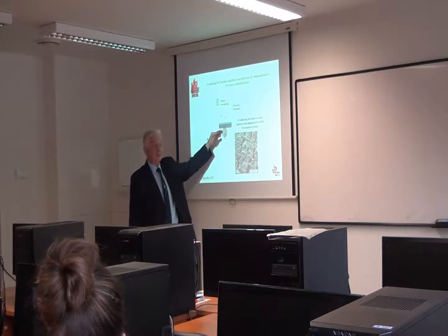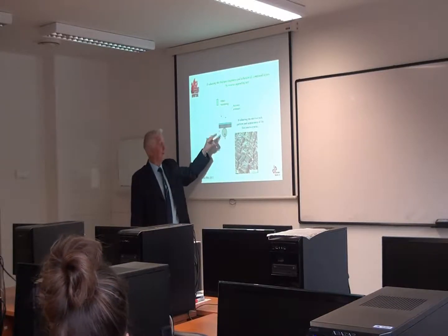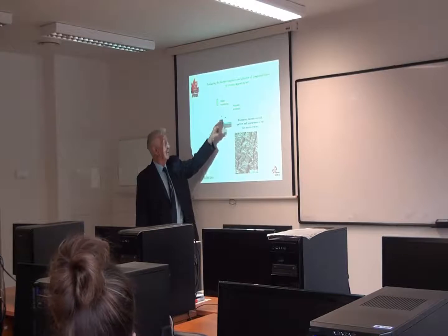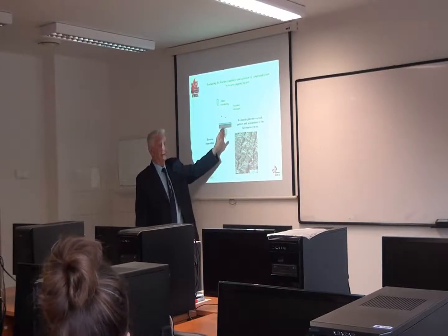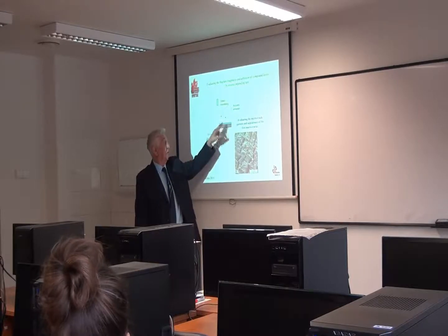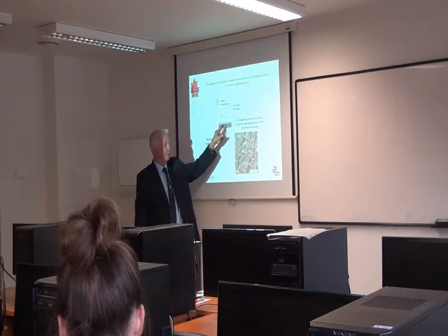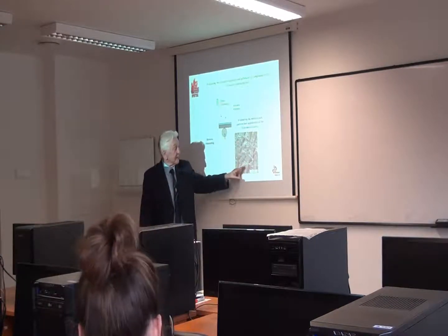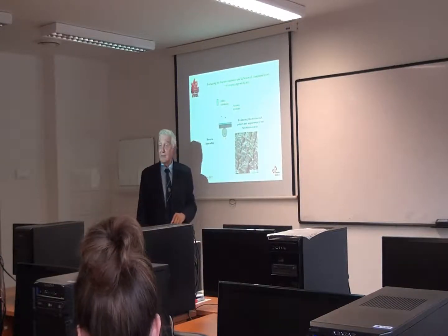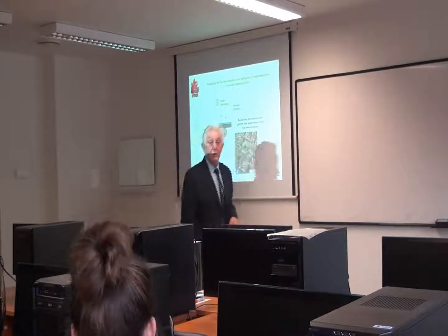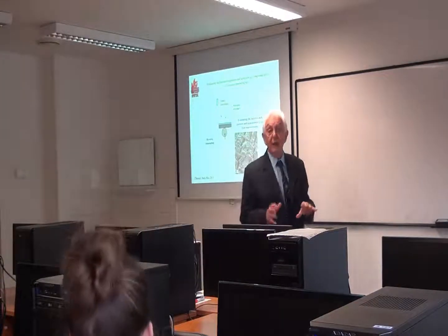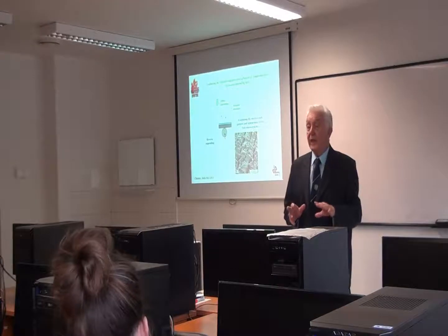Well, we used such a reverse method because the treated surface is outside, and then we applied the force to deform the layer, and we were video monitoring the acoustic emission and the surface layer. This network of cracks will give you a lot if you analyze how this layer will behave.